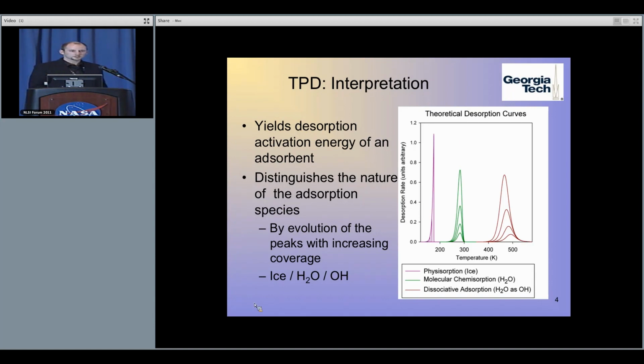And then hydroxyls will actually come off if you heat to high enough temperature, and they desorb as a second order process, where basically two hydroxyls have to become mobile on the surface, but they won't desorb until they find each other, react to form, in most cases, water, and then we see water desorption.